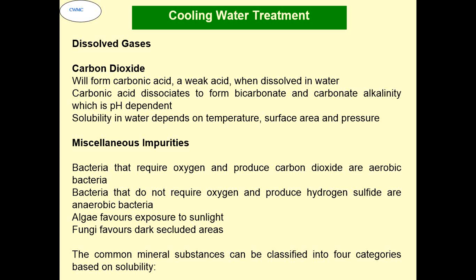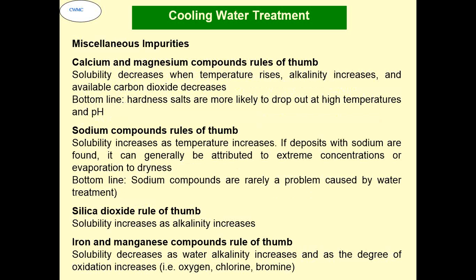The common mineral substances can be present in four categories based on solubility. For calcium and magnesium compounds, solubility decreases when temperature rises, alkalinity increases, and available carbon dioxide decreases. Hardness salts are more likely to drop out at high temperature and pH. Sodium compound solubility increases as temperature increases. If deposits with sodium are found, it can generally be attributed to extreme concentrations or evaporation to dryness. Bottom line is, sodium compounds are rarely a problem caused by the water treatment. For silicon dioxide, the rule of thumb is solubility increases as alkalinity increases. For iron and manganese compounds, solubility decreases as the water alkalinity increases and the degree of oxidation increases, for example, with the presence of oxygen, chlorine or bromine.